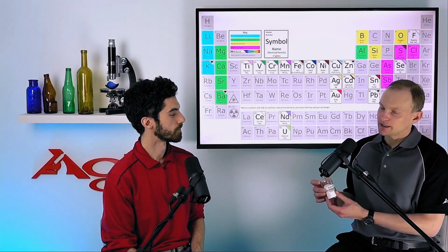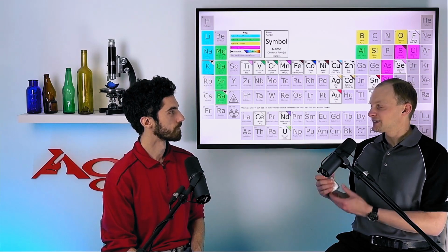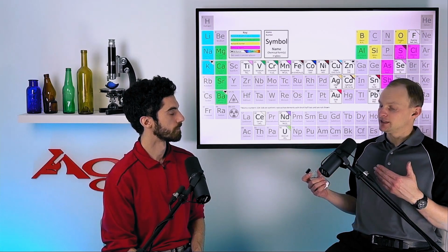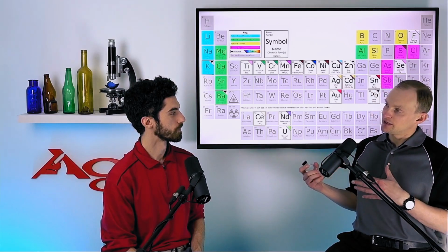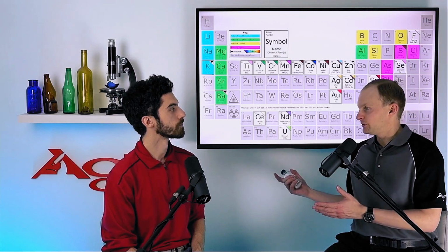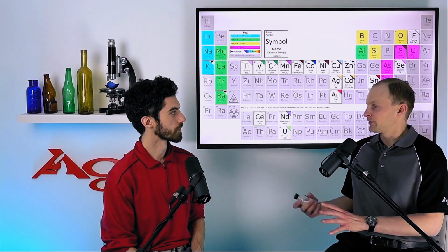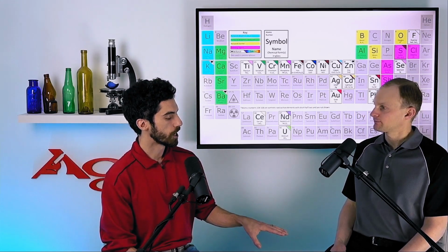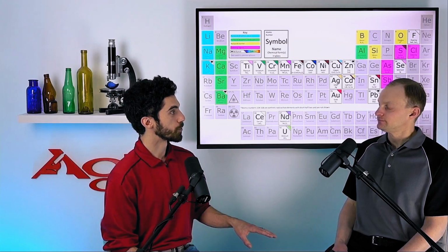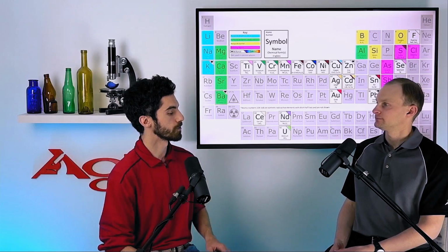Now, sodium carbonate is kind of interesting because that CO3 carbonate group doesn't stay in your glass, because ultimately everything's going to be oxidized in our glass composition. And so that CO3 gets driven off in the form of CO2, carbon dioxide, which leaves during the initial firing and melting process. Right. So this has been a long-time component of glass making in particular. This dates back all the way to the Egyptian era, thousands of years ago.